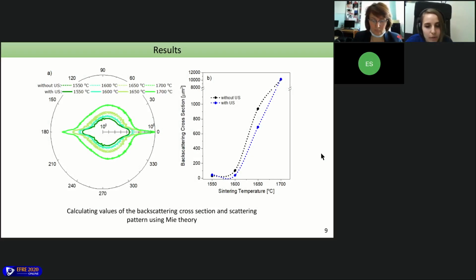According to our estimates, the luminous efficiency of the obtained ceramics is directly connected with diffuse reflection, as was demonstrated previously: with a decrease in the reflection of the excitation light, the luminous efficiency increases, which is quite logical. At the same time, the luminous efficiency with US remains unclear from the presented results, and the decrease in luminous efficiency at 1700 degrees is also not clear. And we use Mie theory to understand and to explain this phenomenon, scattering calculation.